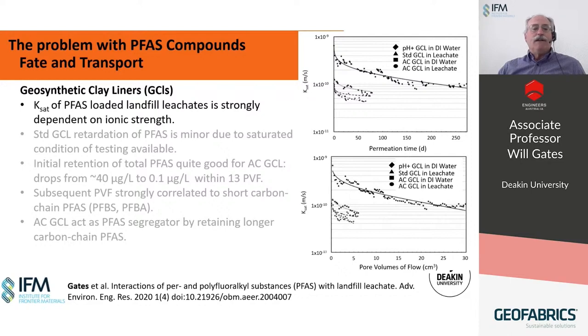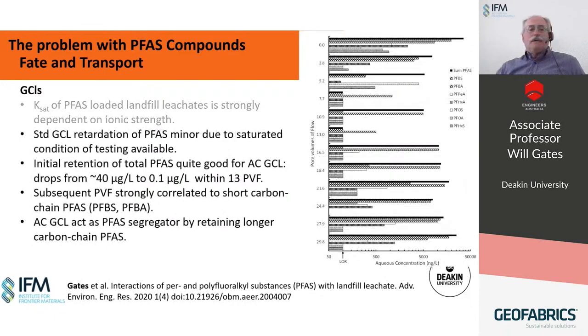The difference, again, is that our geosynthetic clay liners have a much lower saturated hydraulic conductivity because we can manufacture them in such a way that we have low porosity, high density, and a high tortuosity. So what we found is with standard GCLs that we only have a minor retardation of PFAS.